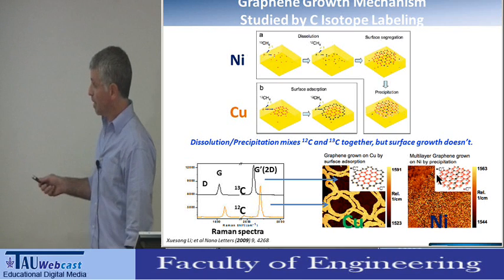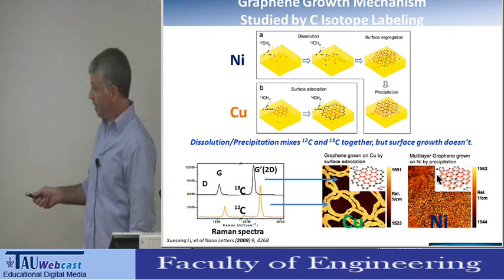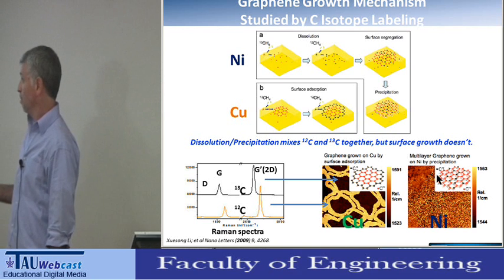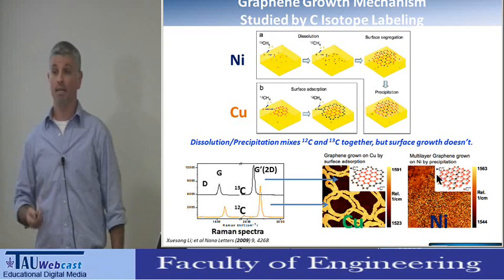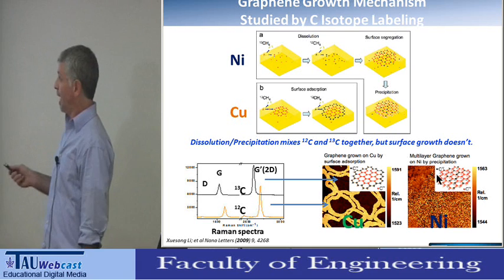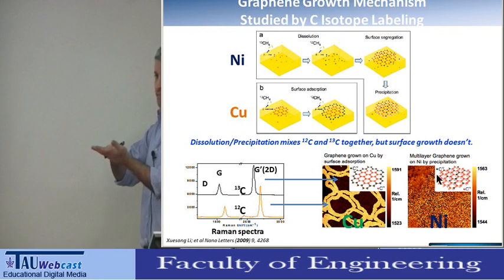But when you do it on copper, it turns out that because of the very low, almost zero solubility of carbon in copper, the hydrocarbon decomposes on the surface of the metal.